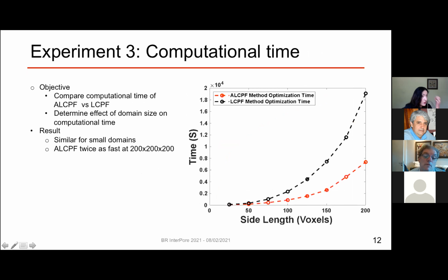The third experiment was on computational time. We wanted to know how much better we're doing with adjustable level cut Poisson fields versus its immediate parent, the level cut Poisson field. And we wanted to know what is the effect of domain size or the sample size on computational time. And what we found is that the result, so this is the domain size and this is the time, is pretty similar for small domains, but as the sample size increases, meaning the size of the material sample increases, we achieve dramatically faster results with our modified model as opposed to the original one.